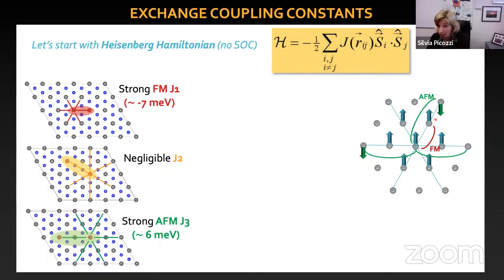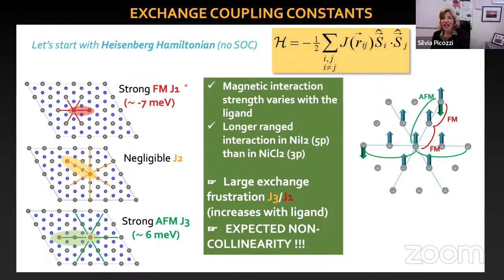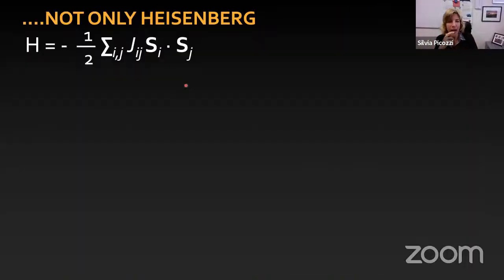But you see that I cannot satisfy all the interactions at play, because if I place this anti-parallel to this one, then it cannot be parallel to this one, which is what the J1 would tell. So this tells you that already at the Heisenberg level, we expect some non-collinearity. We have some frustration in the system, so we expect some complex spin ordering.